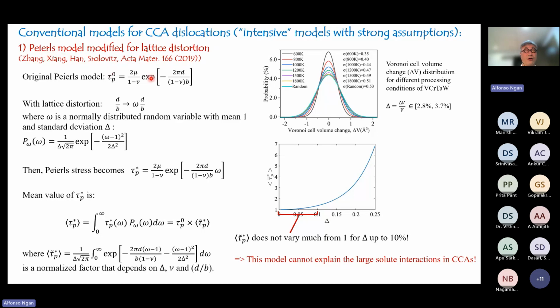And here they take the original Peierls-Nabarro model, which everybody knows could be written in this form in textbooks, but then they give perturbation to this d, which is the interplanar spacing. The perturbation is to account for the lattice distortion when the system now has different elements of different sizes. So they subject this d, this interplanar spacing, to a normal distribution. And after some Fourier transform analysis, they concluded that the Peierls stress would be elevated by a factor, which is this term in here.